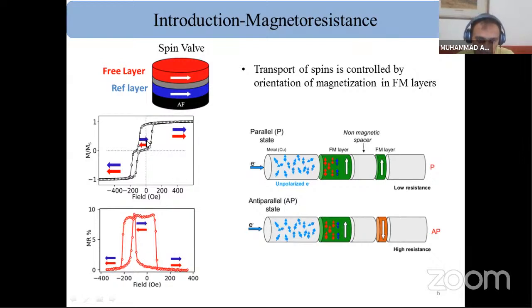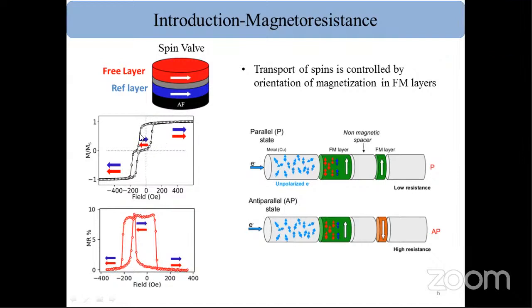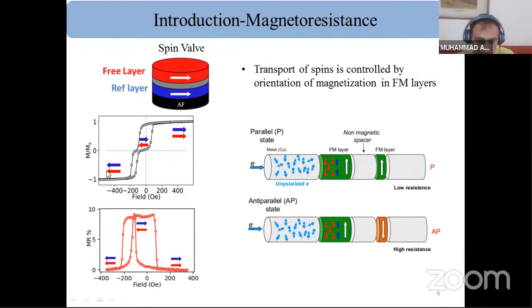Here you can see a static characterization of a spin valve. You can see an anti-parallel state when the spins are in anti-parallel direction, and this is a parallel state, and this is a parallel state but in the opposite direction. This is a transport characterization. You can see a high resistance state when the spins are anti-parallel, while the low resistance state is when spins are in parallel direction.